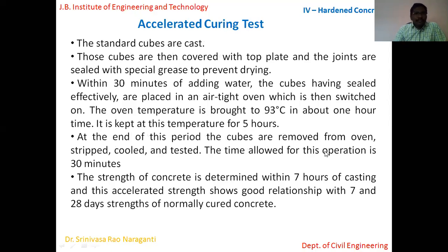So what we do is we initially prepare a standard cube. Usually the standard cube that we use is 150 mm by 150 mm by 150 mm. You prepare a cube, then those cubes are covered with plates on all sides, and joints are also sealed so that no evaporation happens, nothing goes outside. Then within 30 minutes of adding water, the cubes have to be sealed completely.